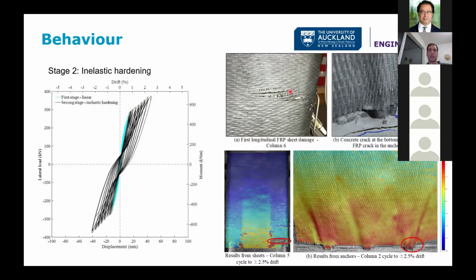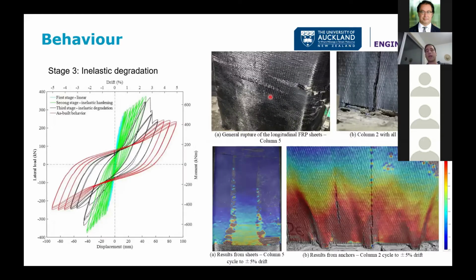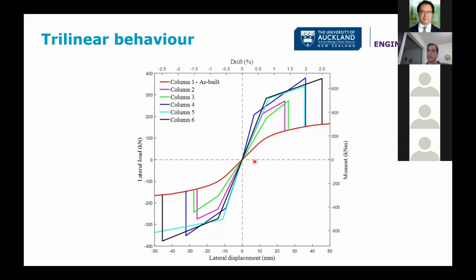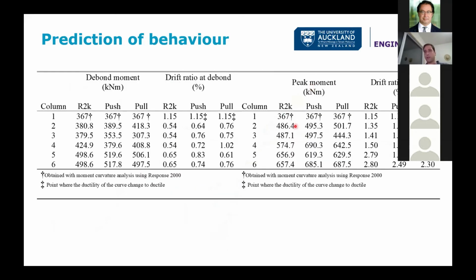Then in stage 3, the FRP ruptured slowly, depending on the column, sometimes more slowly than others. And then when all the longitudinal FRP was broken, the as-built behavior was resumed, which summarizes to this trilinear behavior: linear elastic, inelastic hardening, and then as-built, which give us 2 points, the debond point and the peak point. Now, there are a lot of numbers in here, but don't try to read them, just listen to what I'm saying.